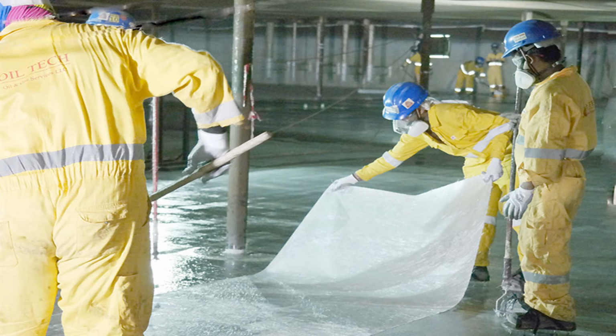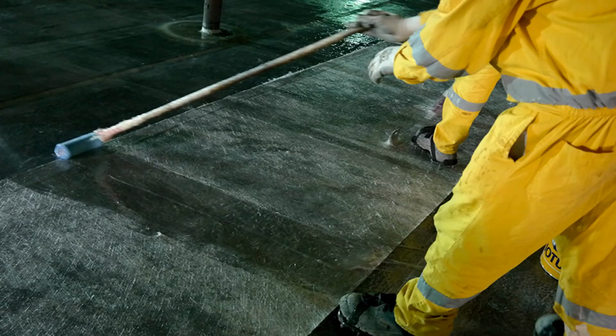A properly selected and applied lining can protect the steel from internal corrosion up to 10 to 20 years. Thick film fiberglass linings are considered secondary bottoms that are bonded tightly to the storage tank. When properly selected and applied, they prevent leakage due to internal corrosion for 10 to 20 years. If the supporting steel bottom is perforated, these linings also can help minimize the problem of exterior corrosion by providing enough strength to bridge small perforations.